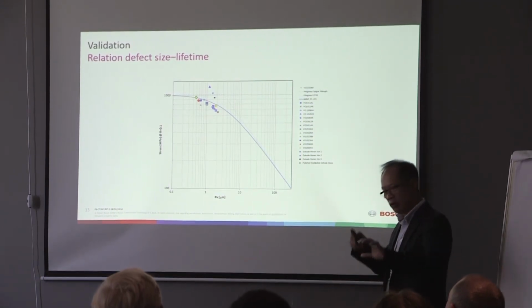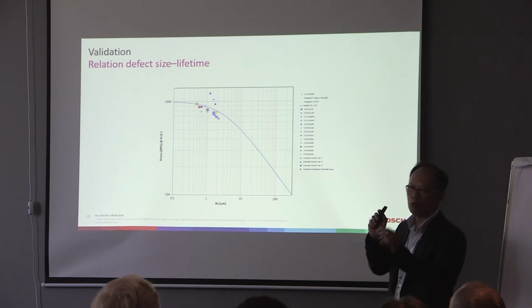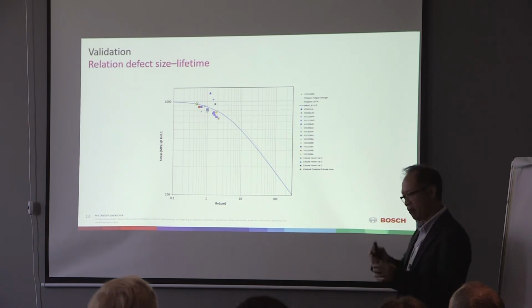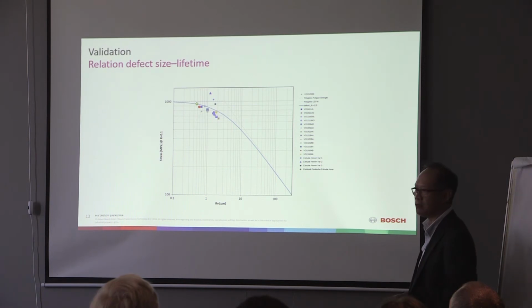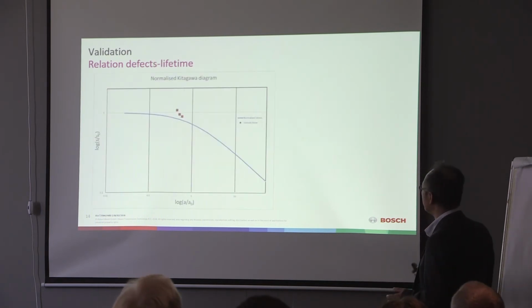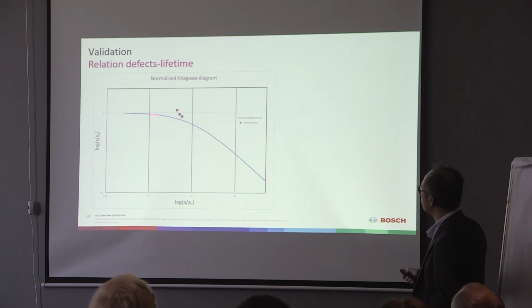So, you know, at high pressure we are pushing some paste through the opening in order to polish the notch. And by that, you not only make a very nice surface finish, but you also introduce a lot of residual stresses. Okay. And so we have those residual stress measurements and just want to show them again. And here we have to normalize the data because we have two dimensions there and we need to normalize them. And this is how it looks compared to the theoretical one.